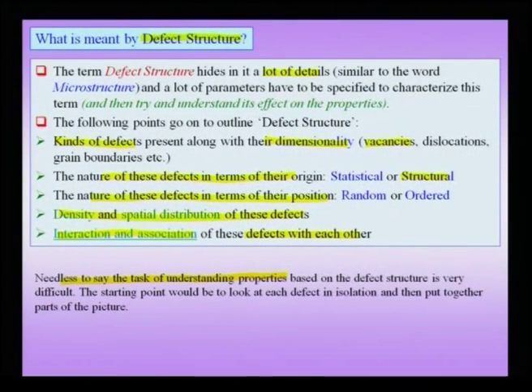This will be the theme of understanding which we will take up in the coming slides. This endeavor is extremely complicated and barely being undertaken today, because defects like a vacancy or a precipitate represent not only a single length scale but multiple length scales. A single defect like a dislocation could have its expression at multiple length scales — the stress field of a single dislocation pervades about a few tens of nanometers, but dislocations sitting along grain boundaries represent a different length scale.